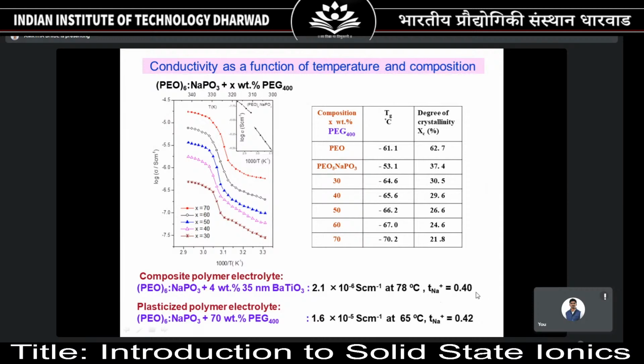So then what else was conducting? Electronic was 0, ionic was roughly 0.4, that is 40%. What else was moving along? What is the species which is conducting? Basically, in the case of polymer electrolyte, the disadvantage is that here you don't have simply sodium ion alone. You may be having other species like Na2, Na3, which are multiple complexes, because here you have oxygen of polyethylene oxide and sodium, which are linked. There may be different kinds of ion groups forming, and those ion groups are also mobilized in the matrix.